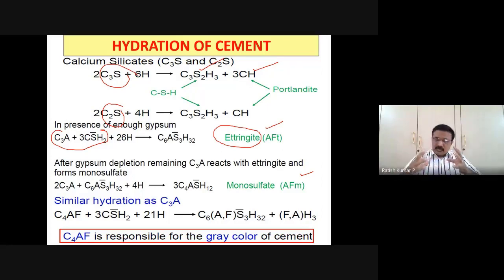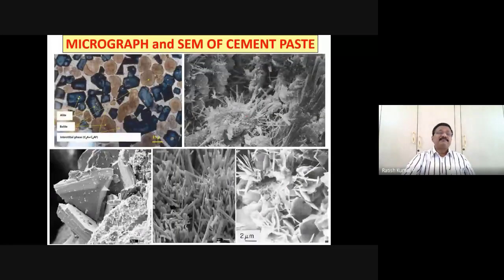But this ettringite is also going to create some durability related problems, and that we have to concentrate upon. So once the ettringite converts into monosulfate, I think it is safer. But while it is ettringite, because these are needle-like crystals, they tend to grow in size and break the interfacial transition zone between the CSH, the cement phase portion, and then it creates cracks, and then it creates very large durability problems. We'll try to see that.